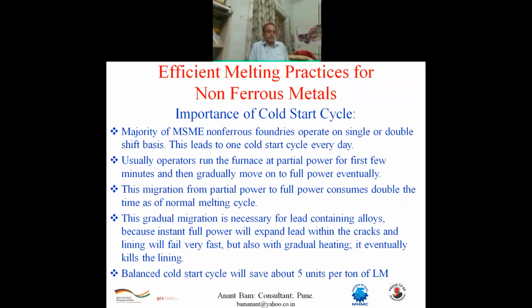Cold start cycle. We saw that during cold start, if we start the furnace with full power, then we can save on energy. But if we are dealing with leaded materials like pre-cutting brass or leaded bronzes or gunmetals, then we have to be very, very careful during the cold start. We have to see to it that the lead is gradually heated and it takes its liquid condition and drips down into the crucible bottom. Until then, you cannot go for full power. So it's a tricky situation.